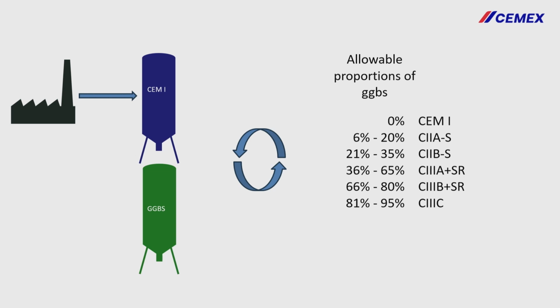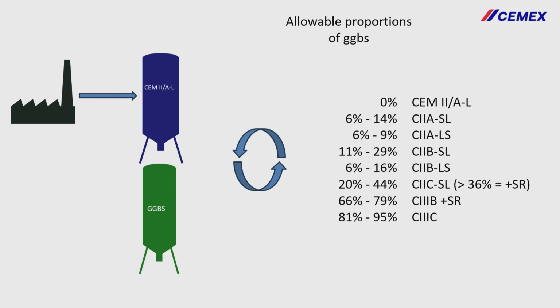CEM I, 0% GGBS, all the way up through to 95%, which is a CIIIC, and all points in between: CIIA-S, CIIB-S, CIIIA plus SR, CIIIB plus SR. Okay, so that's what you would have seen. What we can now do is stock CEM II/A-L. So CEM II/A-L is pre-blended clinker plus limestone fines. We produce it at Rugby, we pre-blend it at Tilbury from a Cemex perspective, and it's typically got about 15% limestone fines in it. So you're immediately lowering your CO2 per tonne from CEM I to CEM II/A-L.